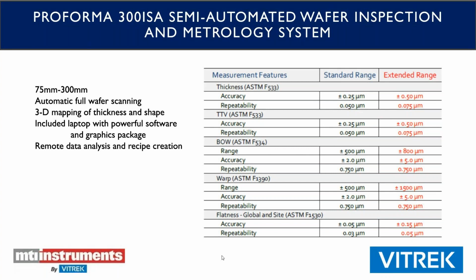And as you can see with the features here, it does meet the SEMI and ASTM standards. You can see for thickness, it's the ASTM F533. Bow is 534, warp is 1390, and the flatness spec is to the F1530. So if you need more information on that, I'm happy to provide that. But those are the specs for this.